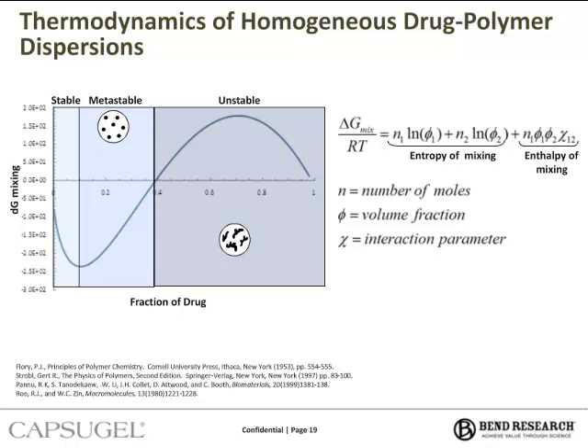And there's three distinct regions in this graph. The first region is the stable region, and this is where the delta G is negative, and the drug and the polymer will mix spontaneously and will not phase separate. Now the next region is the metastable region, and this is where the free energy is negative, so they will mix, but the slope is positive. So in this region, the solid dispersion will eventually phase separate.